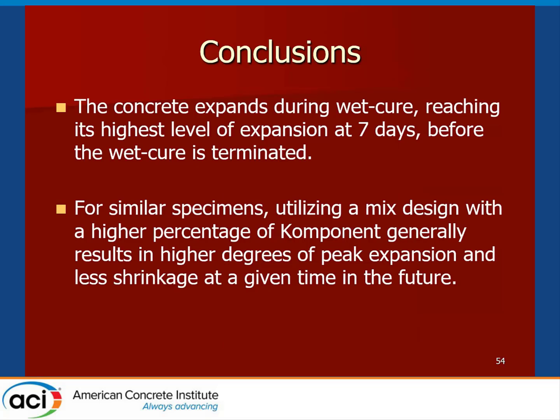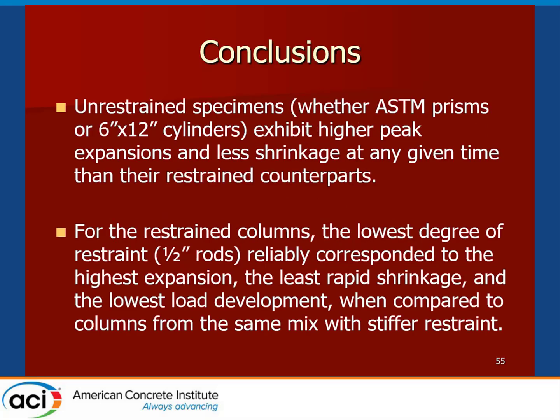In conclusion, the concrete expands during wet cure, reaching its highest level of expansion when wet cure is terminated — in this case set at seven days per standard practice. A higher percentage of mineral expansive admixture results in higher peak expansion and less shrinkage at a given future time period. Unrestrained specimens for a given component percentage resulted in higher peak expansions than their restrained counterparts. For the restrained columns, the half-inch rods — the lowest degree of restraint — allowed the highest level of chemical expansion and the lowest amount of load development compared to those with a stiffer restraint system.